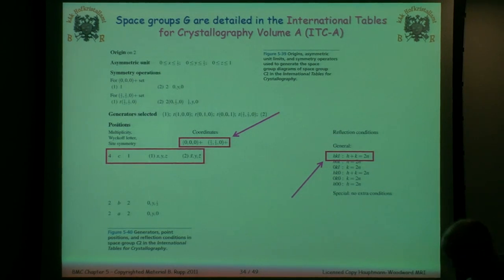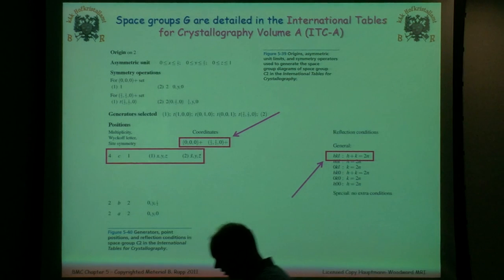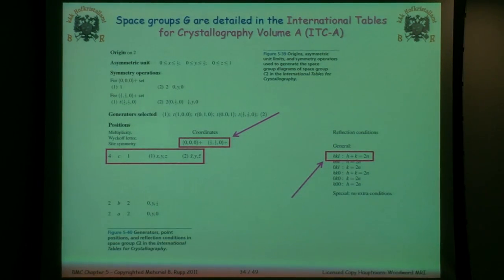If you collect some data, you index your crystal, you integrate the data, scale it, and then use it in refinement, and you get phasing information, but the structure is not refining to something reasonable, it's staying at about 40 or 50% for the R and the R-free, then you need to check your reflection conditions and see if it is the right space group. And that's where you have to start looking at the data rather than looking at what the program is presenting. Many programs will actually allow you to look at this. Xtriage will point this out. A few other ones will point this out.